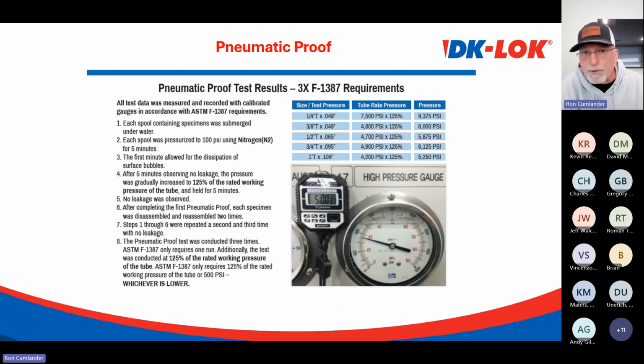So we built all the spools and we followed the procedure for the pneumatic proof test. And once we completed it, there was no leakage. We could have stopped, but we chose not to. And in the pneumatic proof, ASTM F-1387 gives us the option of testing at 500 PSI or 125% of the working pressure of the tube. So we chose the more severe pressure rating of 125% of the working pressure of the tube.